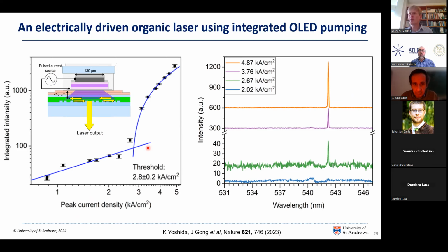So when we have a distributed feedback laser such as this structure, if we have just a planar film, then we get essentially a Lambertian emission pattern coming out with a cosine of the angle dependence in intensity. With the diffractive structure, we already get some level of directionality in the beam, and that somewhat depends upon the properties of the grating, to what extent these diffracted peaks dominate over the Lambertian background. This both affects the spatial but also the spectral dependence.